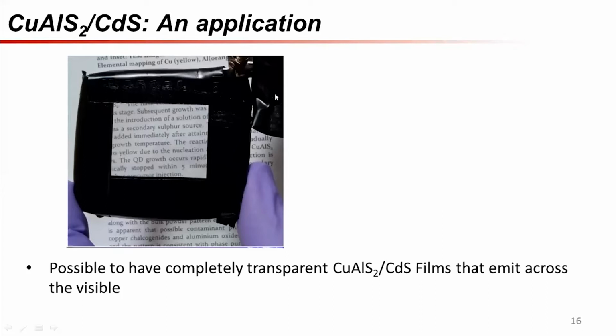So, for example, take the case of copper aluminum sulfide. In the case of copper aluminum sulfide and cadmium sulfide, we are getting one behavior. We are having a large Stokes shift. We are getting emission. If we made copper aluminum sulfide zinc sulfide, we find that this is a system which actually expels its electrons to the nanocrystal surface, and this leads to photocatalytic behavior. So, zinc sulfide is not a tool to be used directly as a direct substitute for cadmium. It's a good angle of investigation, but it does not always work.